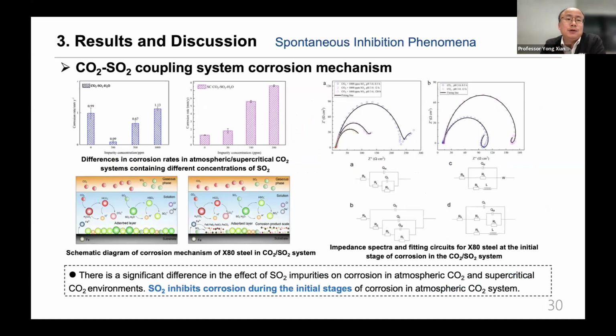For the CO2 transport and injection systems, we also would like to check the SO2's effect on the corrosion. Actually, maybe 10 years ago, we thought that when SO2 is injected into the CO2 system as an impurity, it would enhance the corrosion rate. But in our tests, especially for the atmospheric CO2 system, the SO2 reduces the corrosion rate, because we found some corrosion product formed on the steel surface when the SO2 was injected into the system, especially at the initial stage of the corrosion.